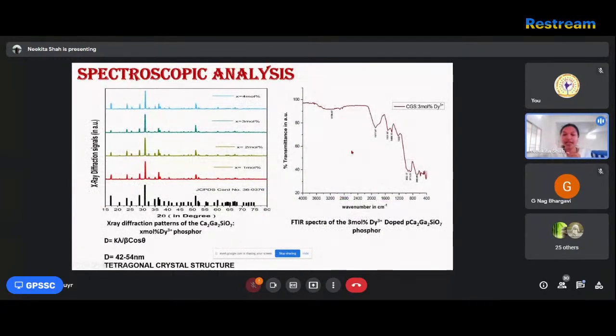This is the FTIR spectra, which confirms the presence of hydroxyl group. This wave number shows the presence of hydroxyl group in the prepared phosphor, and 1900 to 1700 wave number shows the presence of carbonate groups in the prepared phosphor.